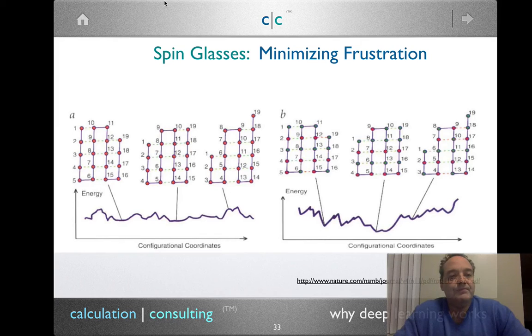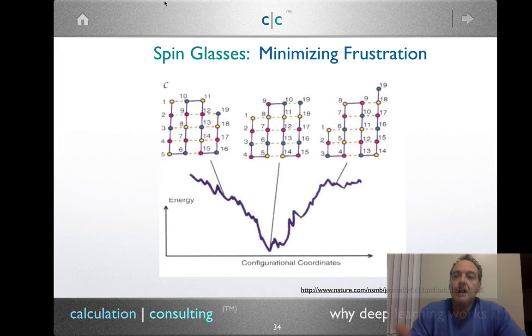So imagine, for example, you have a polymer, and it's just folding on itself. And these are just the configurations. It's trying to find different ways to fold. It's a string, and it's folding on itself. And if there are no connections, it can do anything. It can be in any configuration. As soon as you start saying that the polymer has to have some connection point, so imagine that you have a string, and the string has to be tied together at a certain point where it sticks together, all of a sudden, this changes the number of configurations it can have. So if you have a polymer which has lots and lots of connective points, where it's sticky and sticks together, then it doesn't have as much entropy to sample, and its energy landscape will begin to funnel, and it will become ruggedly convex.